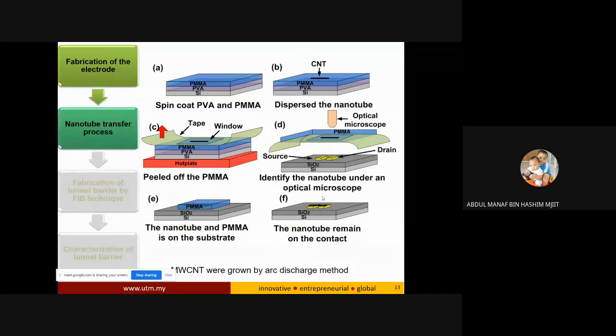This is how we do what we call the mechanical transfer technique. Basically, we prepare a structure of silicon, PVA, and PMMA. Next, we disperse carbon nanotubes on the PMMA, and then we use a tape and peel off the PMMA together with the carbon nanotubes. Then we put this tape containing carbon nanotubes on the electrode and press it. Finally, we can get the carbon nanotube on the electrode. Here we can understand that the nanotube is in a suspended condition.